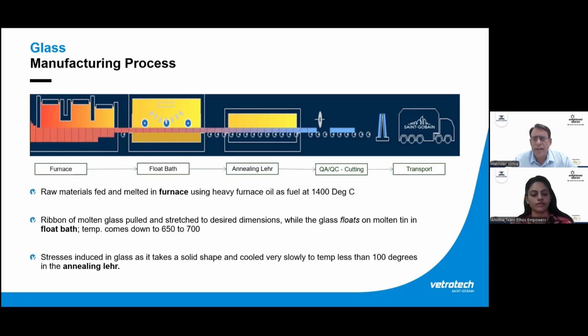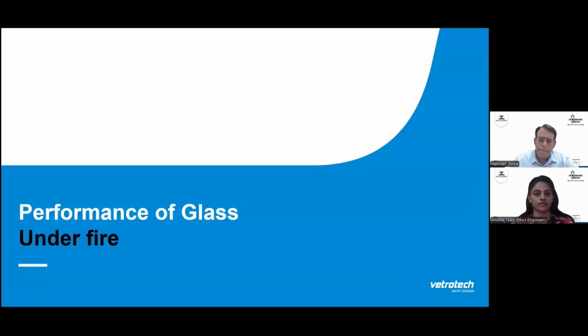Now, when it comes to fire rated glass, for certain fire rated glasses the raw material composition is slightly different. We sometimes add alkaline earth metals so that we increase the melting point of the glass. As you can see here in the float bath, the temperature of the glass will go up to 650 to 700 degrees Celsius, whereas when we add alkaline earth metals, or it could be a borosilicate glass, it can go up to even 900 plus degrees Celsius. So this is how the different types of fire rated glasses are made.